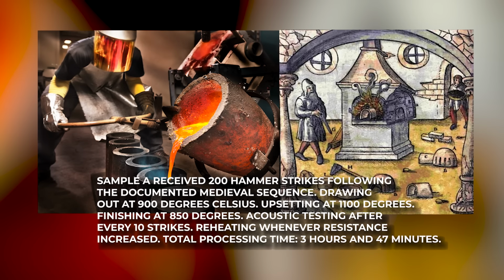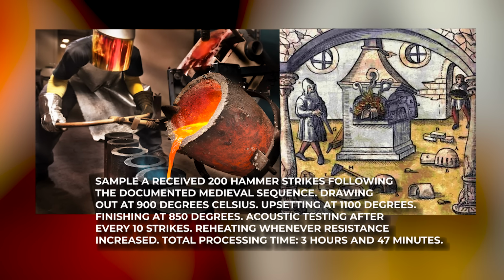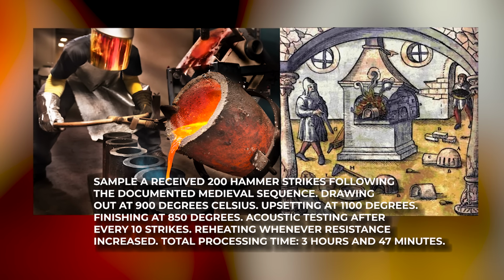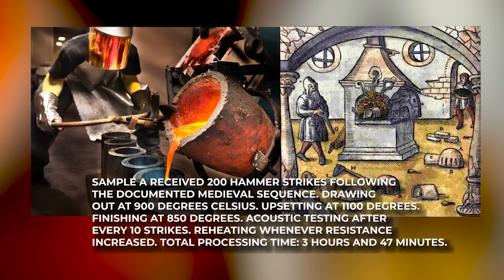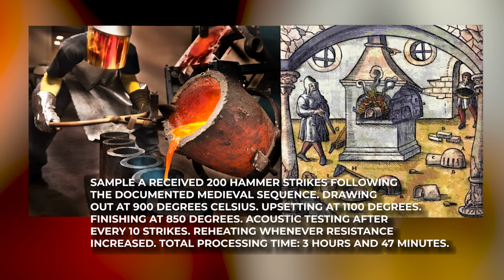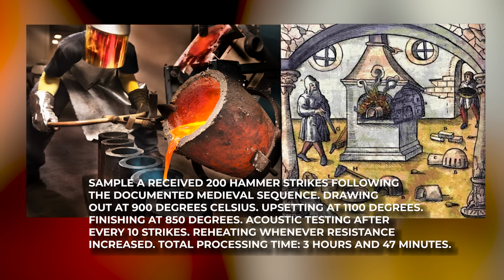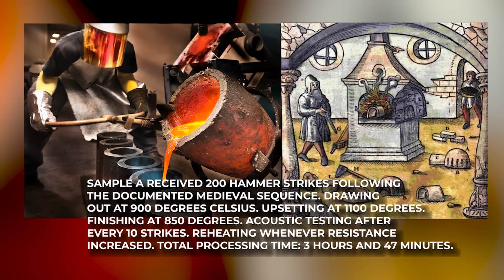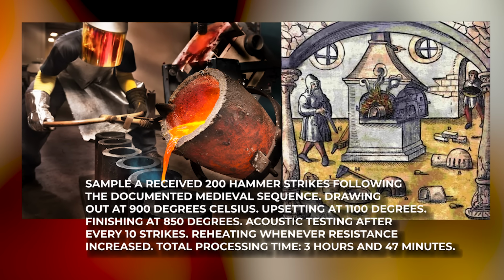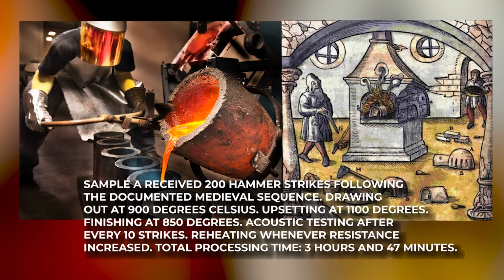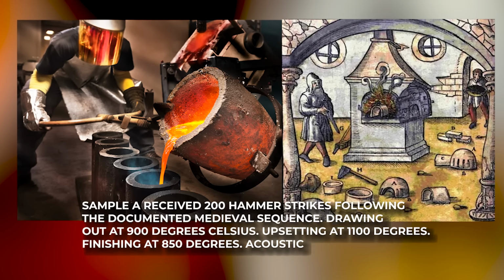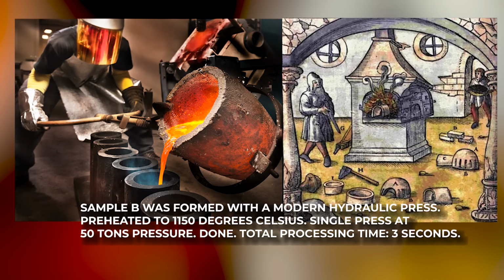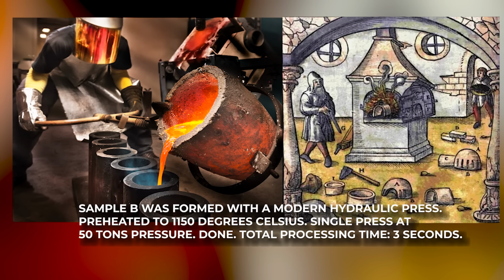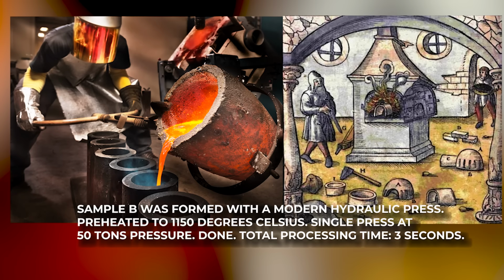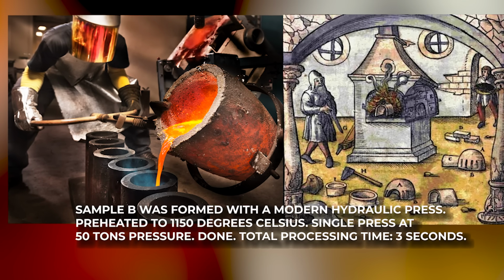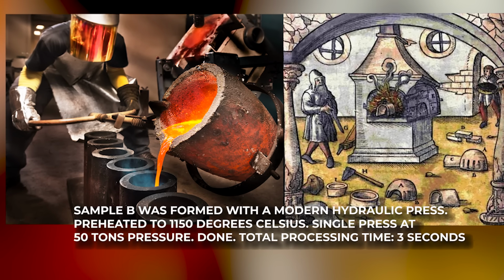Sample A received 200 hammer strikes following the documented medieval sequence, drawing out at 900 degrees Celsius, upsetting at 1100 degrees, finishing at 850 degrees. Acoustic testing after every 10 strikes, reheating whenever resistance increased. Total processing time, 3 hours and 47 minutes. Sample B was formed with a modern hydraulic press, preheated to 1150 degrees Celsius, single press at 50 tons pressure. Done. Total processing time 3 seconds.